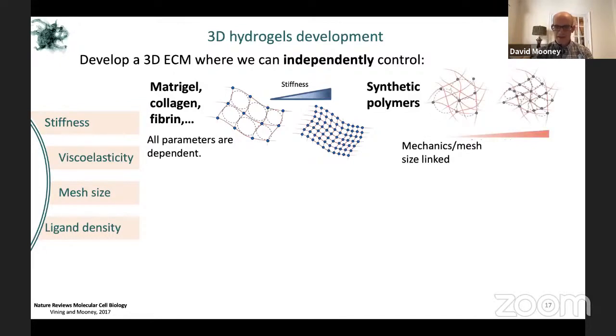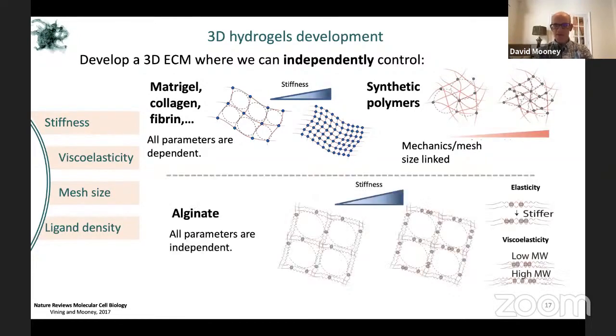Now we can take a classic synthetic polymer approach to make hydrogels instead. Like the alginate system, if the cells don't mediate adhesion themselves, we can decouple the ligand density and type by covalently conjugating it to the polymer chains after we form them into gels that are either more or less stiff. But again, as one varies the crosslink density in a traditional polymer system, one varies the mesh size or diffusional transport. Now, the reason we use these alginate gels is because of this cross-linking structure, or this cross-linking between blocks of these sugars that I previously described.